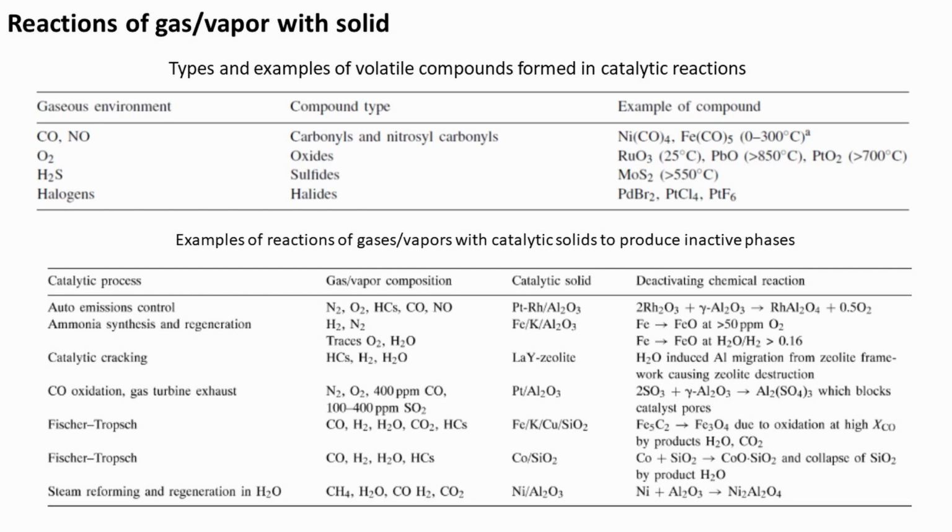Loss of nickel metal during CO chemisorption on nickel catalyst at temperature above 0 Celsius is also a serious problem in view of the toxicity of nickel tetracarbonyl, the rapid loss of nickel metal, and the ill-defined adsorption stoichiometries. Researchers avoid using CO chemisorption for measuring nickel surface area, and use hydrogen chemisorption instead.